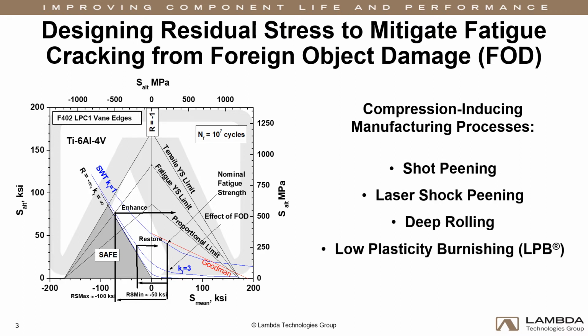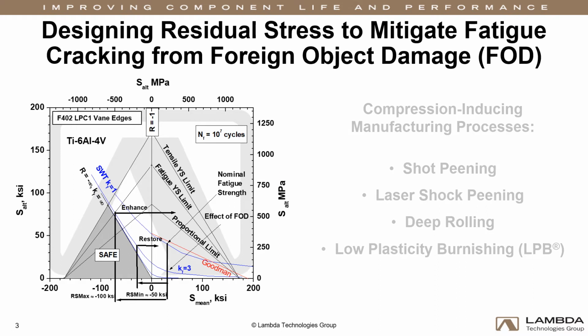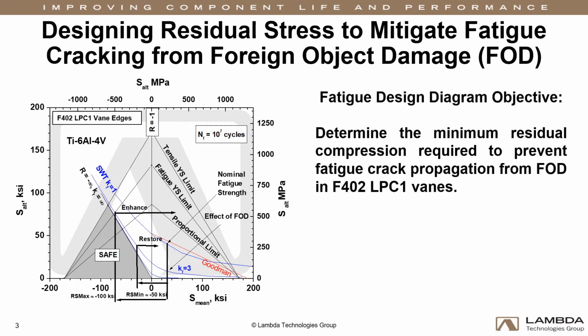The depth, magnitude, and distribution of the residual compression are designed specifically for each component and application to produce optimal performance. This means going through a process to calculate the minimum residual stress required to mitigate fatigue cracking from FOD. We do this using our proprietary fatigue design diagram. Within the triangular region marked safe, the FOD-prone region is in a fully compressed state throughout the cyclic loading seen in service. In the absence of tensile stresses, cracks cannot initiate or propagate.